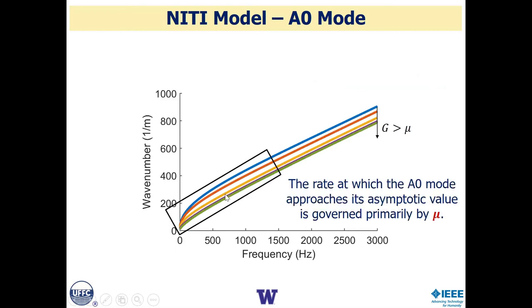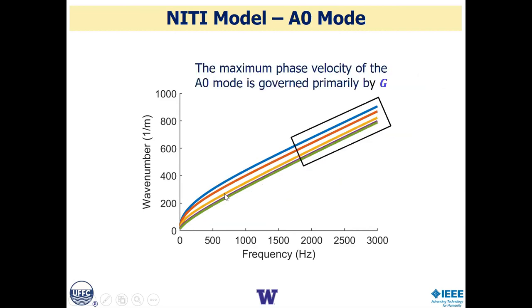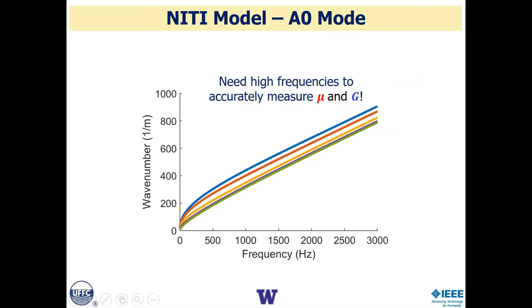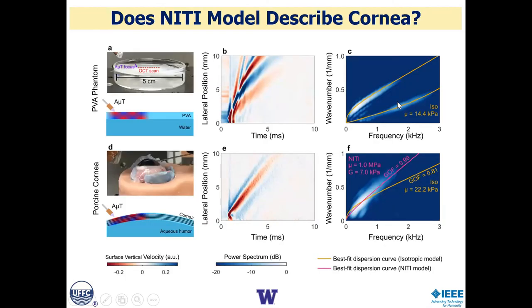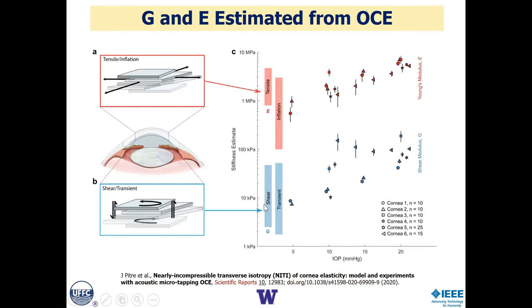The low frequency end is determined primarily by mu. The high frequency end is determined by G. So when you fit, you can simultaneously estimate both mu and G. And that's what we've done. We look at an isotropic phantom and we get the characteristic fits as we would expect. When we look in a cornea, we get this lower order mode where the isotropic model is a terrible fit, but our NITI model giving us both parameters is a perfect fit. And so we're able to estimate simultaneously the shear modulus G and the Young's modulus E.